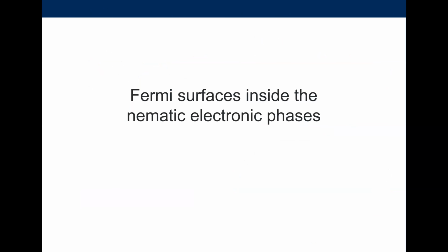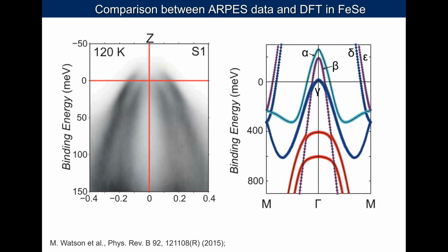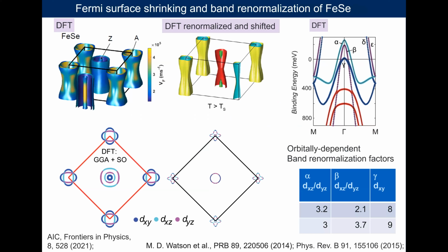Okay, so now I'm going to talk about the electronic structure inside the nematic electronic phases. Here is an ARPES spectra of hole bands in the tetragonal phase. It shows two different crossings, and this is the band structure calculation on the right. So already we see that instead of having 3 hole bands crossing the Fermi level, iron selenium only has 2 of them at the Z point. And here is a direct comparison with DFT. These are 3-dimensional Fermi surfaces with 5 different bands. And in the tetragonal phase, we are only left with 4, and one of them is only left at the Z point. So you have a 3-dimensional little pocket at the Z point.